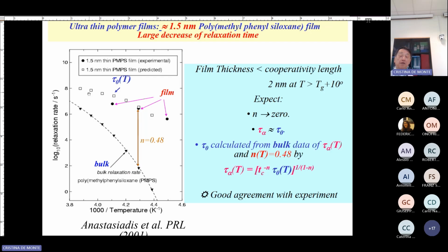This is tau beta. So this is JG. When they intercalated the thin film into this, it became a very thin film, 2 nanometers thin. You expect, as I said, in the coupling model, n goes to 0. As I told you already, instead of seeing tau alpha, you see tau 0. So what is tau 0?